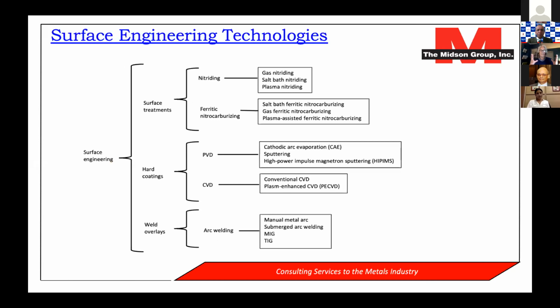So this slide summarizes surface engineering technologies that can be used for die casting and other types of industries, and we're talking about coating the dies. If we call the whole thing surface engineering, I've split it down into three groups: surface treatments, hard coatings, and weld overlays. Surface treatments are the kind of treatments we're used to in die casting: nitriding and ferritic nitrocarburizing, where we are diffusing either nitrogen or carbon plus nitrogen into the surface of our dies, normally about 100 microns or so, and we get hard layers on the surface of our die. Those are pretty commonly used in die casting.